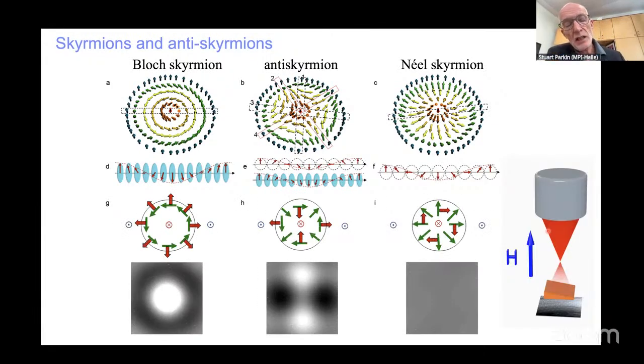And it turns out that for the Bloch skyrmion, you expect to see an intense beam of electrons because they're deflected to either the inside or the outside of this object. So you basically see this simple spot of high electron intensity. Whereas for a Néel skyrmion, the electron beams are deflected by the in-plane components of magnetization circumferentially. So basically you see nothing unless you tilt the sample.